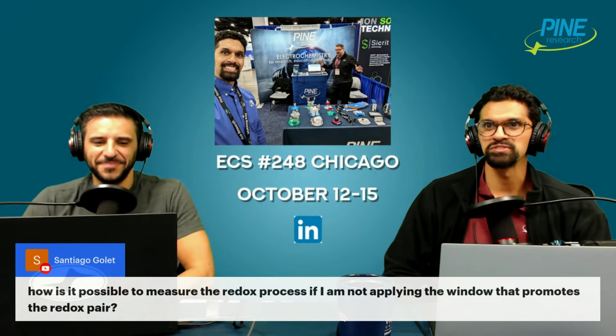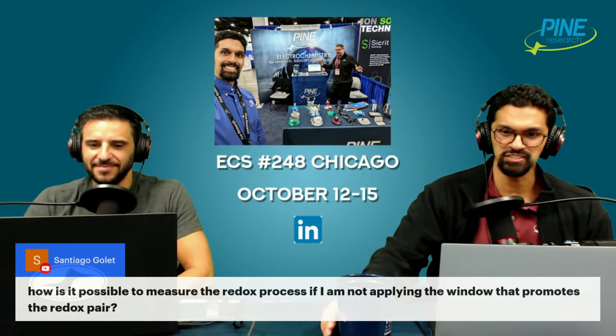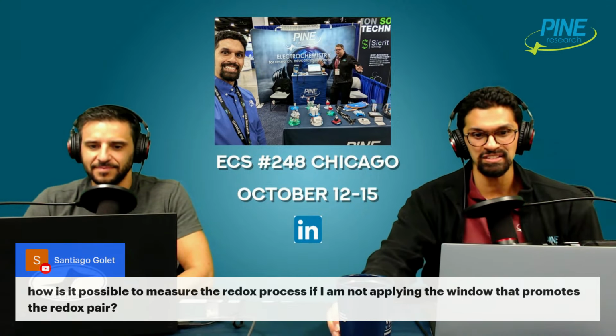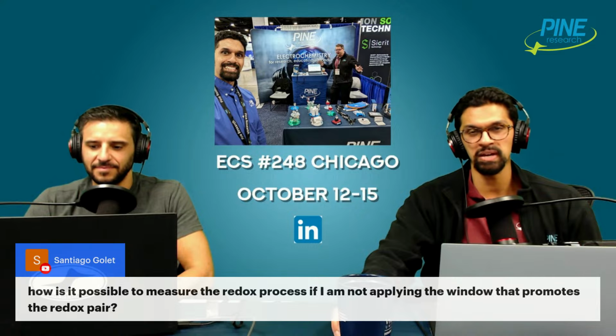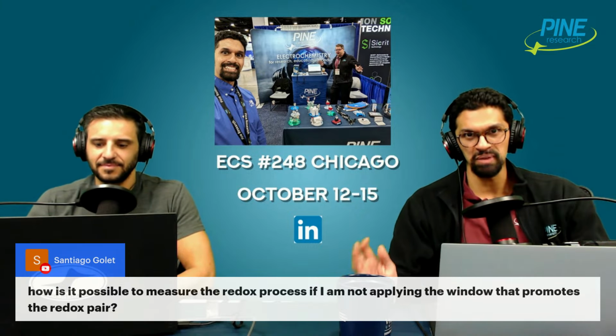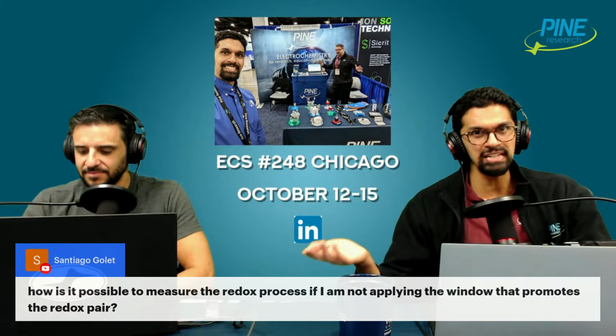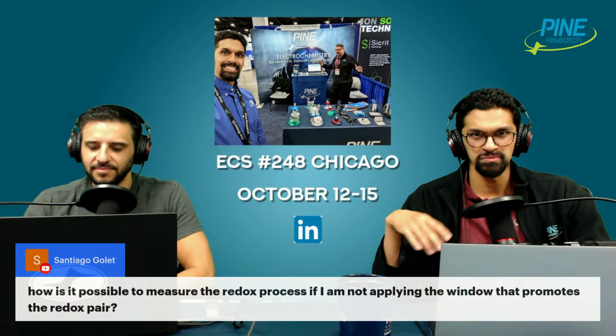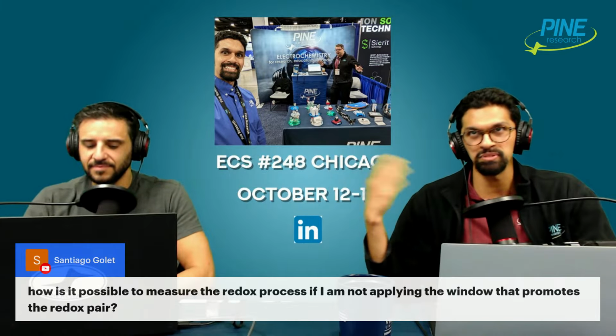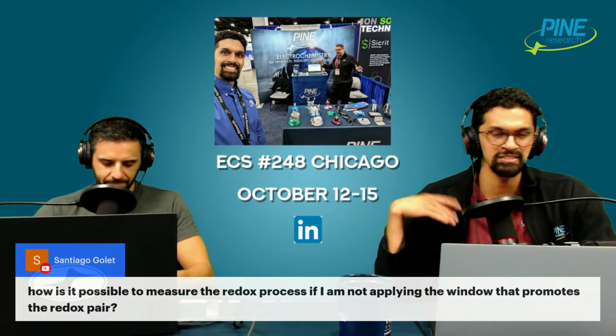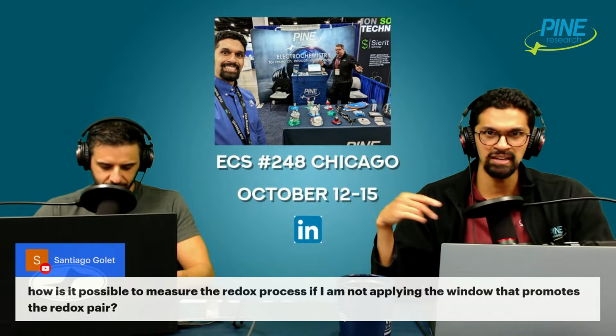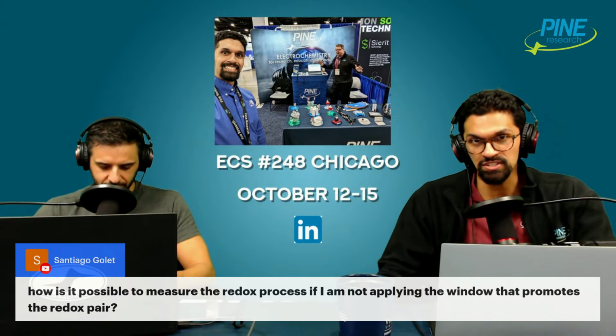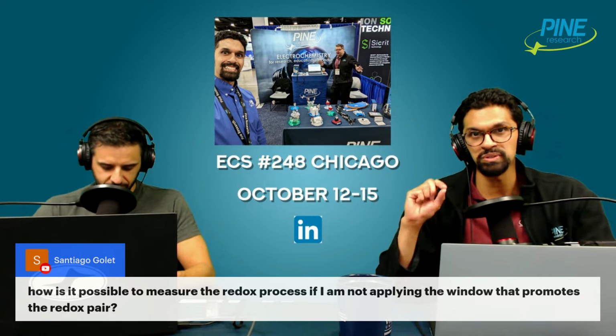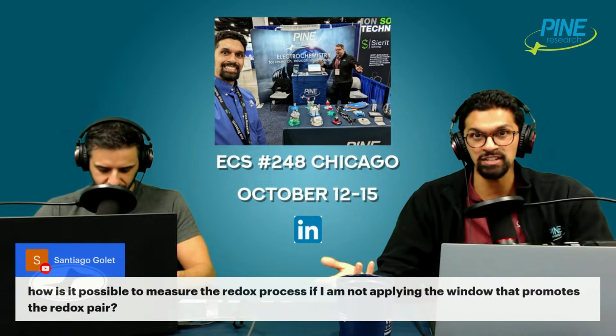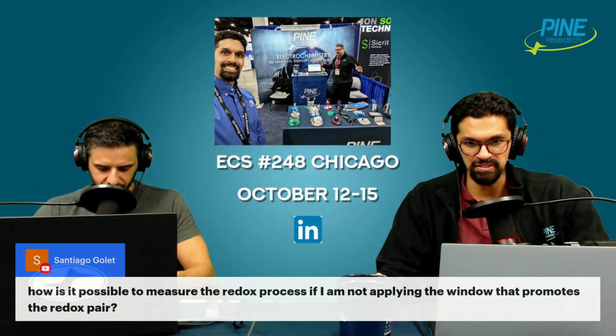So what you want to do in this kind of process is, in EIS, in the parameters, you should be able to set what's called an EIS baseline. Santiago, your thinking is actually completely on point. Why exactly would I have to apply 0.4 volts and then go to OCP and make sure that it's stable? No. If you hold the potential at 0.4 volts and do EIS around 0.4 volts, that's the potential where the redox process is occurring.